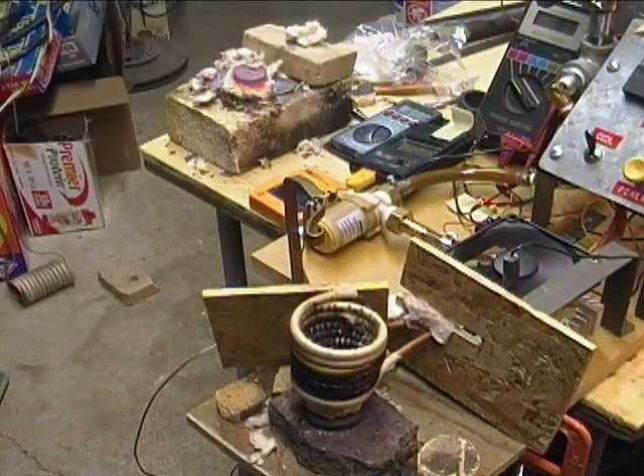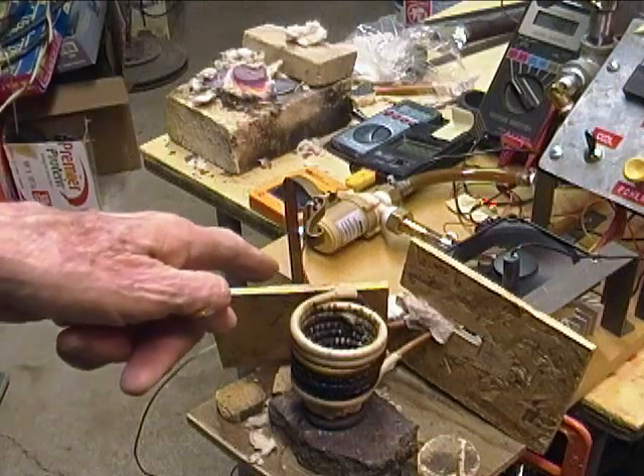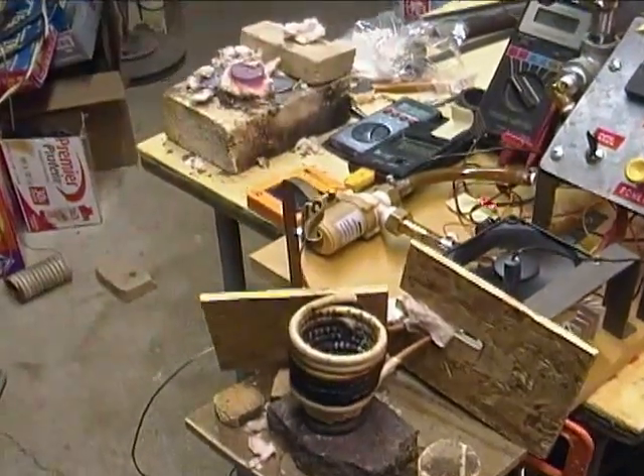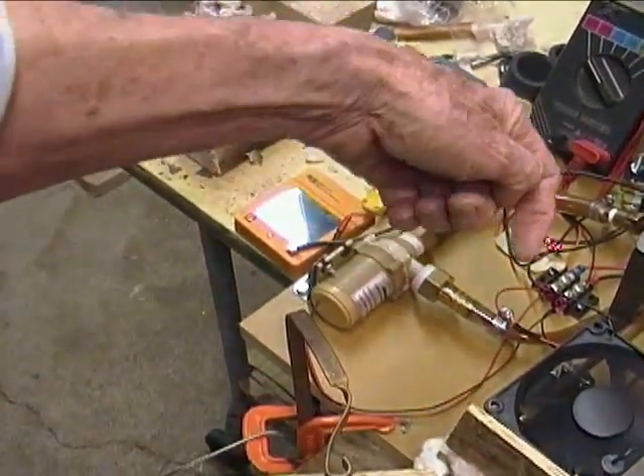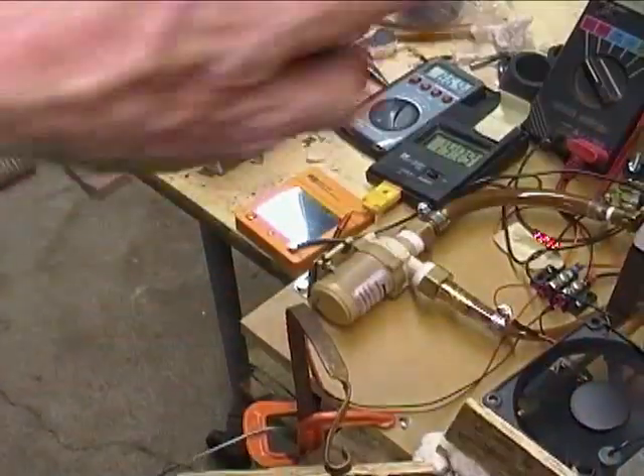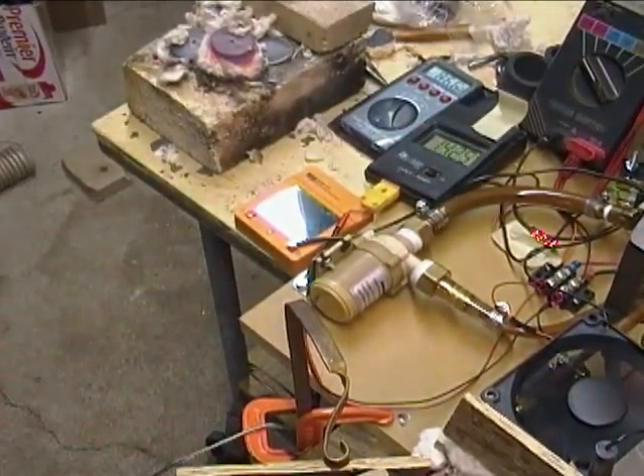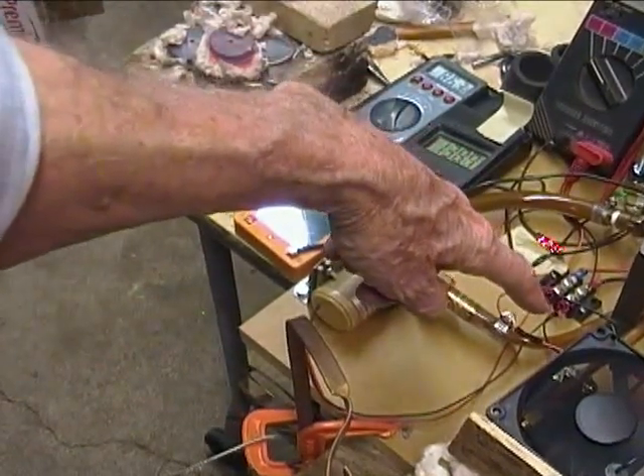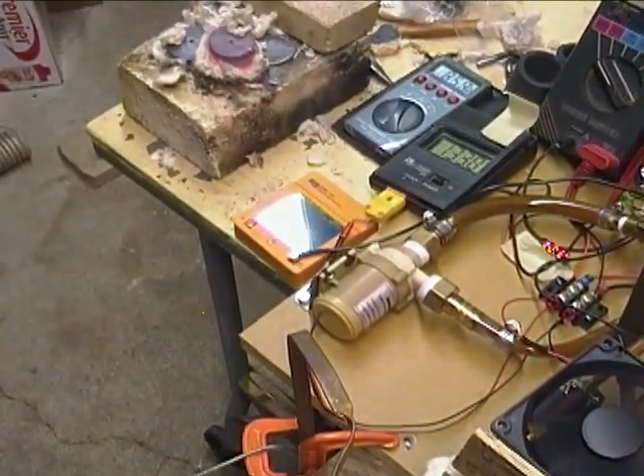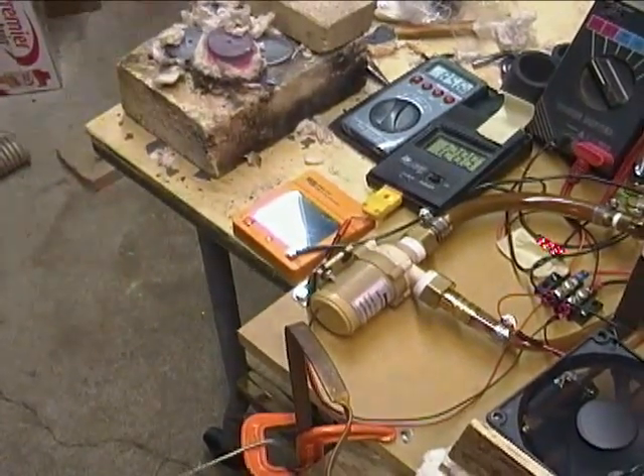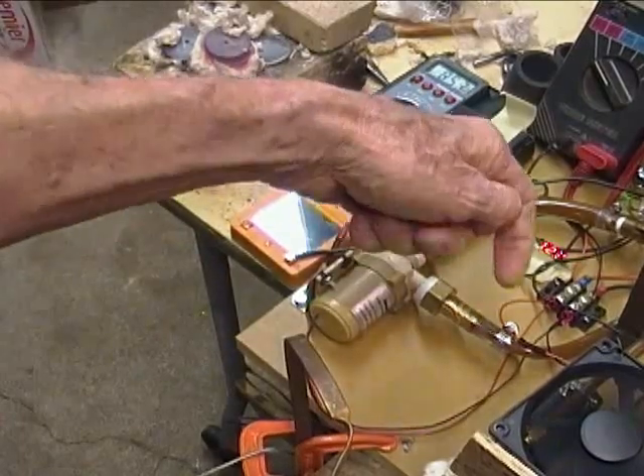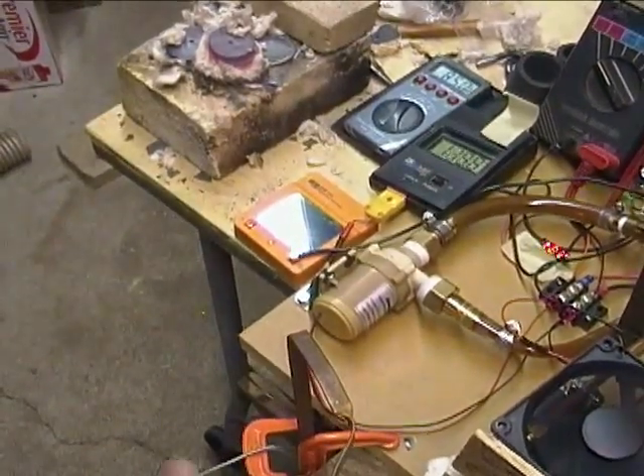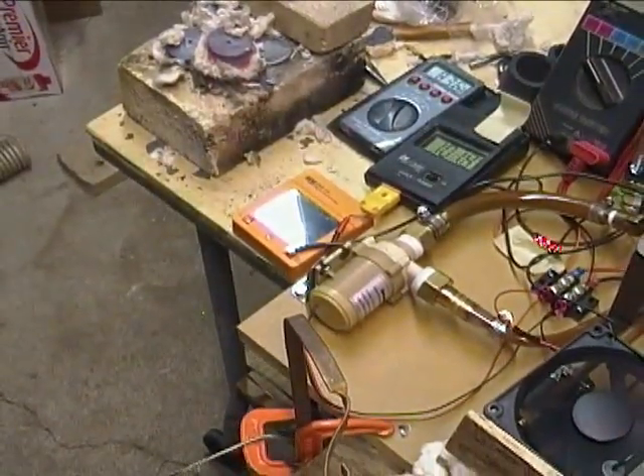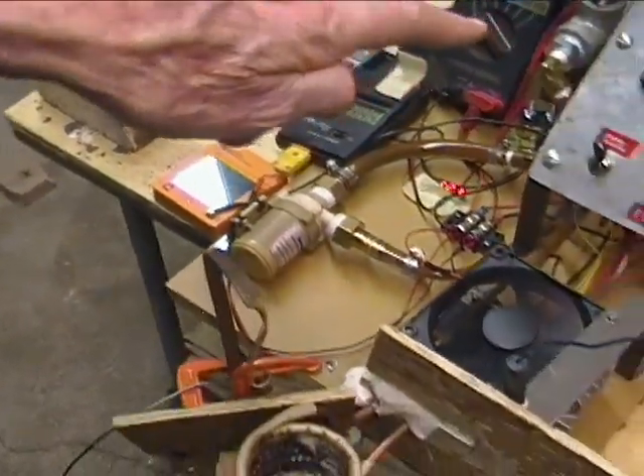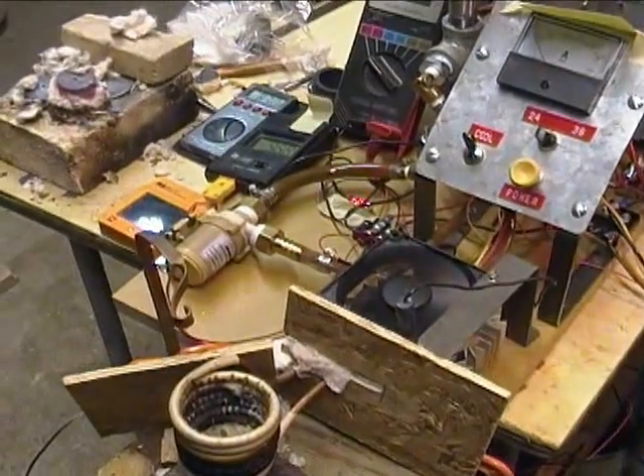And for this test, just to remind myself, when I hooked up this coil, I got my pump leads reversed. So I was pumping out to the top and down to the bottom. So I may have had a few air bubbles that never did get totally cleared out. My mistake. In fact, I see the bubbles moving through there right now, a few of them, which tells me even though the system worked okay, I would have been better off pumping into the bottom of the coil, which would force the coil to fill up, and then overflow into the upper part of the radiator. So if there were any air bubbles, they would be allowed to escape right up here into the expansion chamber.